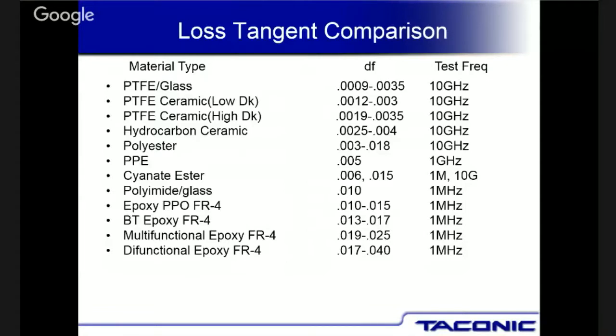Now, if you keep on going, you say, wow, what is FR4? A regular epoxy glass. And you go down to the bottom, and there's a couple different grades of FR4, and I'm going to come back to this and talk about this in a little bit. But you can look at it and you'll say, damn, 0.025. That means 2.5% of the fields actually get lost in the material as the signal is going down the trace. So it actually ends up with a lot of loss, which we all hate in our microwave boards because that contributes to very, very poor board performance.